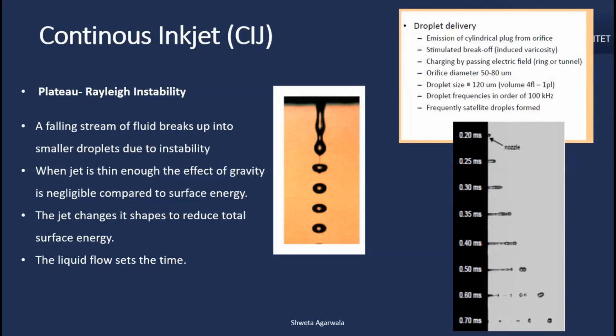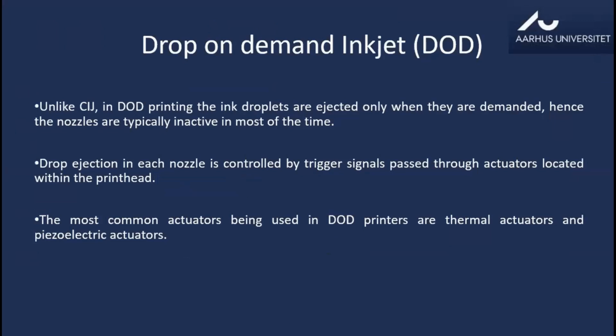And while ejecting out, it separates into these spherical droplets and impacts the surface. Now, this is not a very efficient process, and sometimes you need to have places where you don't want the drops to be. It's good if I were to make a thick square of 2 by 2, 1 by 1 cm, because I need the material everywhere.